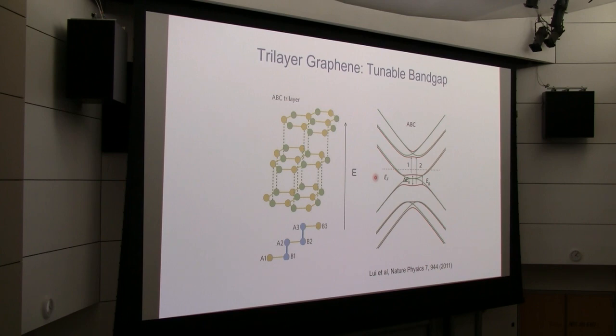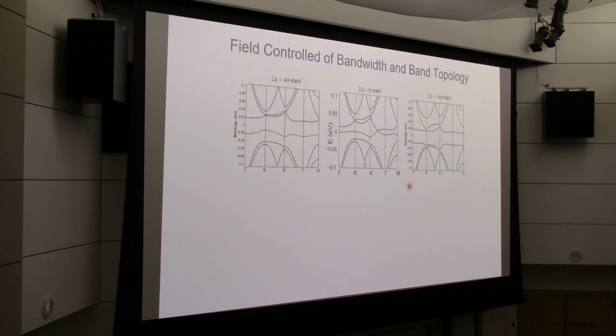Unlike monolayer graphene, which has massless Dirac electrons, trilayer graphene has a reasonably large mass. It can also have a tunable band gap. In a pristine sample, you have zero band gap because of inversion symmetry, since the top A atom and the bottom B atom are the same. By applying a vertical electric field, you break that symmetry because these two atoms now have different potential, and you can create a finite band gap. Now if you combine this trilayer graphene with boron nitride to form a Moire superlattice, all these effects still exist, but now you need to add a smaller Brillouin zone.